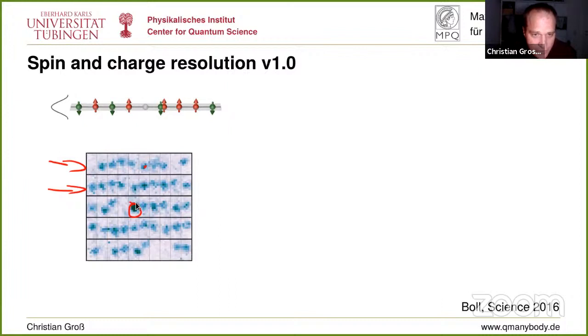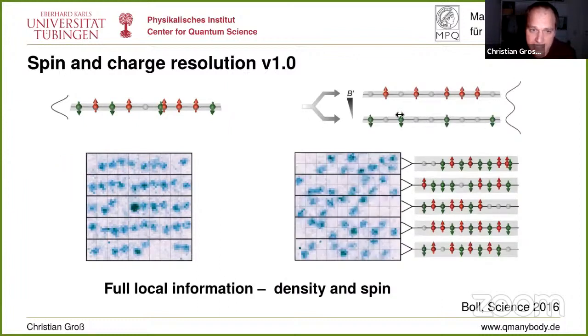What we can now do is a local Stern-Gerlach splitting before we actually raise the superlattice potential. So with 2 wells, as you see here, we split each of those sites vertically in 2. Because of the magnetic field gradient, this forces the spin up atoms to go to the upper side and the spin down to go to the lower side. With this, we get a 1-to-1 identification of all the occupation and density and spin for all the sites.